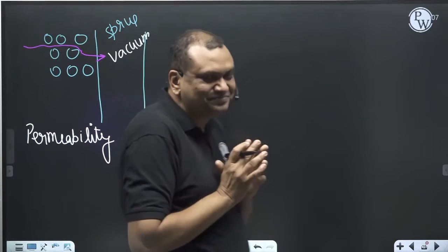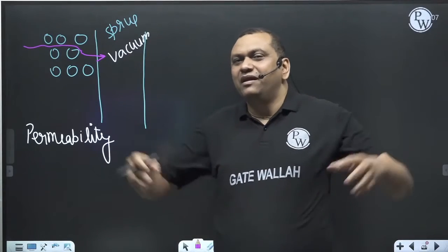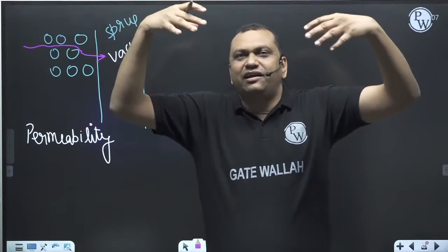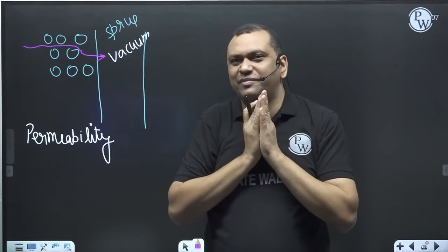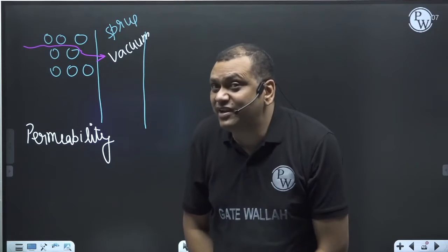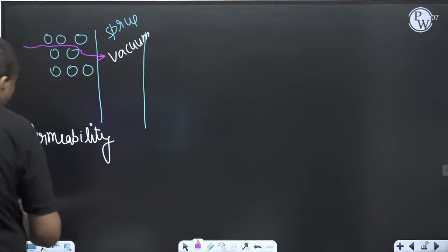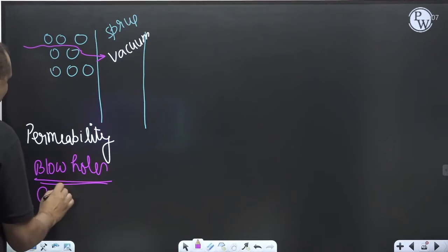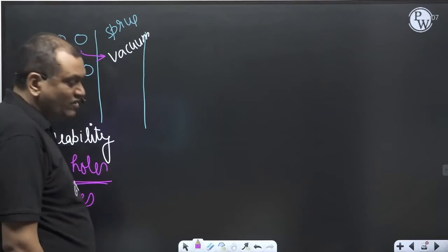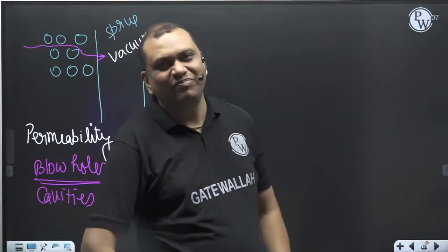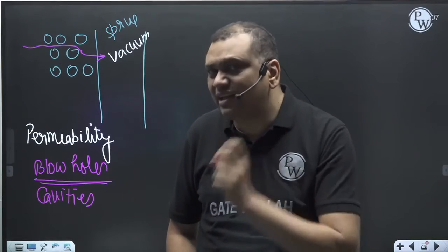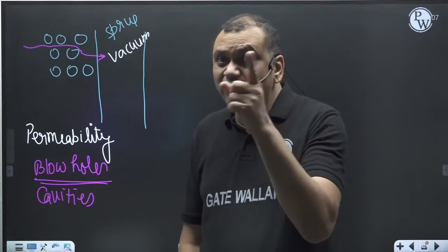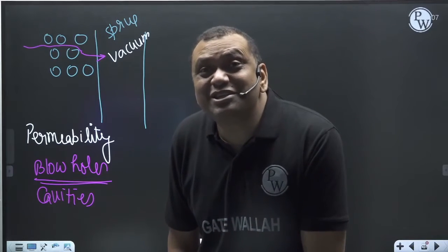Opposite of permeability will happen, because vacuum is inside and outside pressure is atmospheric. Through the sand voids, the atmospheric gases will come and mix with the liquid metal. And once the atmospheric gases mix with the liquid metal, there will be blowholes or cavities inside the casted part. In other words, it will be a defective casting. So anywhere in the gating system, vacuum should not develop.